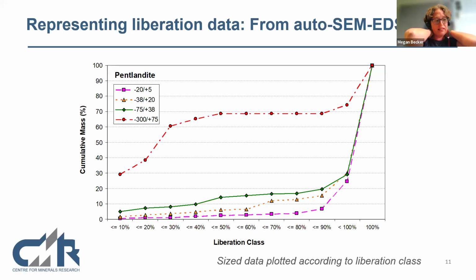Then when the automated systems started coming in, because everything was digitized, we could start working with different liberation classes. And this just uses cut points of 10%. Here's the liberation class, and that's the cumulative mass. Over here, we go from 10 to 20. So any particle that plots there has between 0 and 10% of that valuable mineral in the particle. If a particle plots in this less than 100 class, it's obviously got between 90 and 100% of that valuable mineral in the particle. And then you can plot this cumulative curve and look at the trends between the different size fractions. So this is one of the ways people look at liberation data.